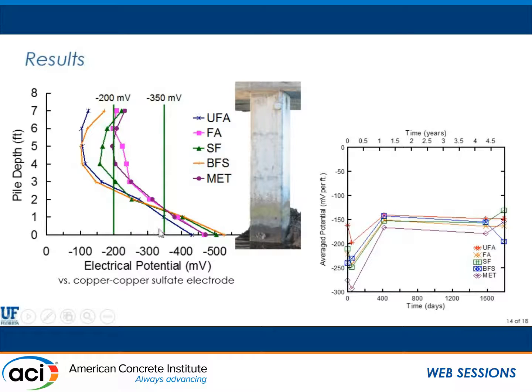But keep in mind down here where the concrete's wet with salt water, you're going to get those high readings anyway. So what you're really looking for is the movement of the upper levels, the splash zone, and the upper portion of the tidal zone moving towards that more negative number as you start to see the potential for corrosion to occur there.